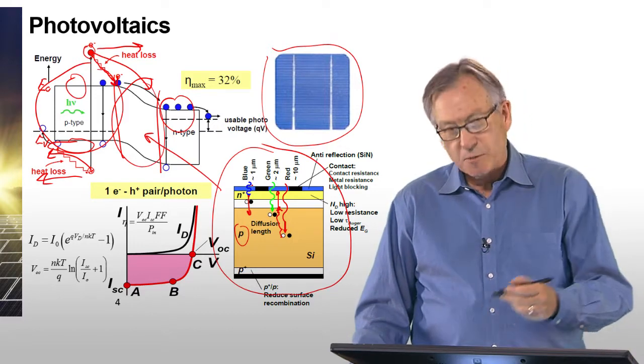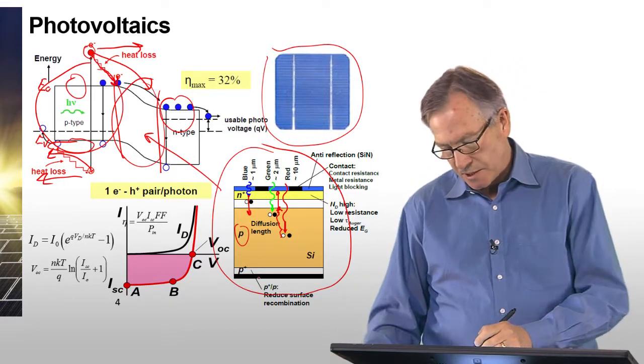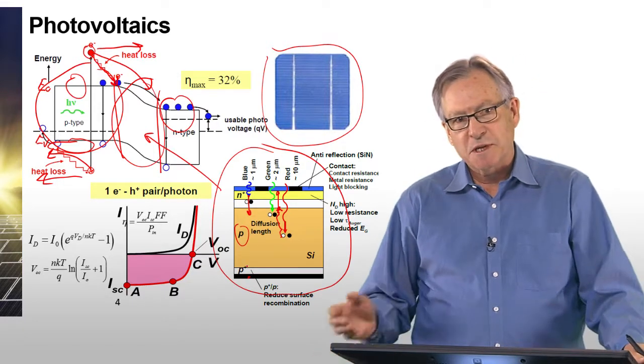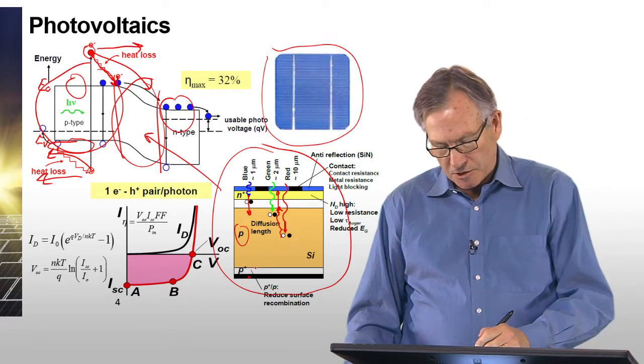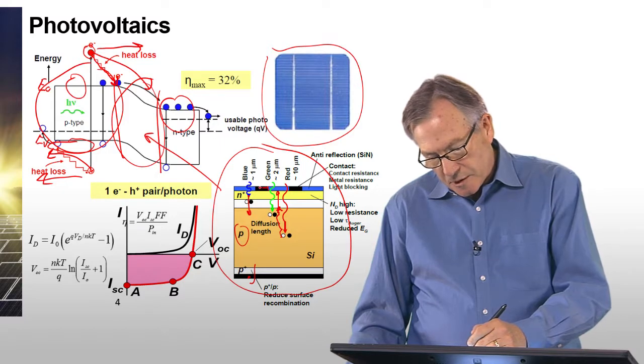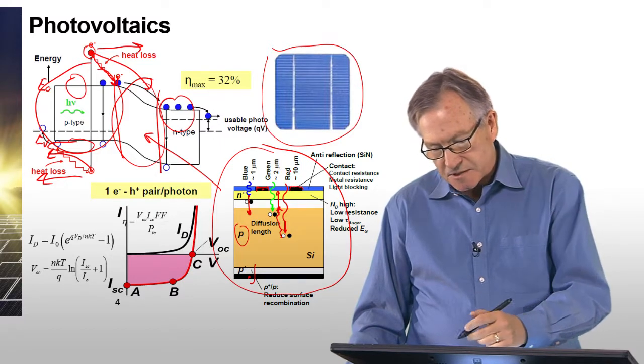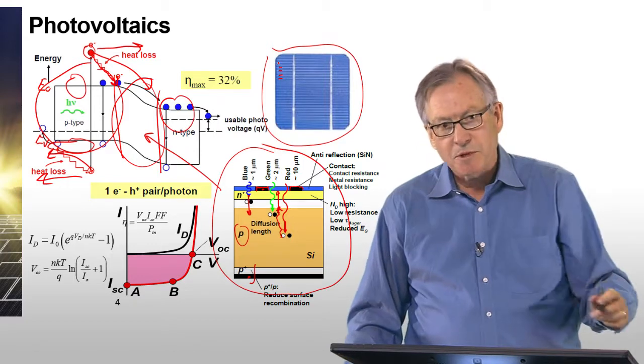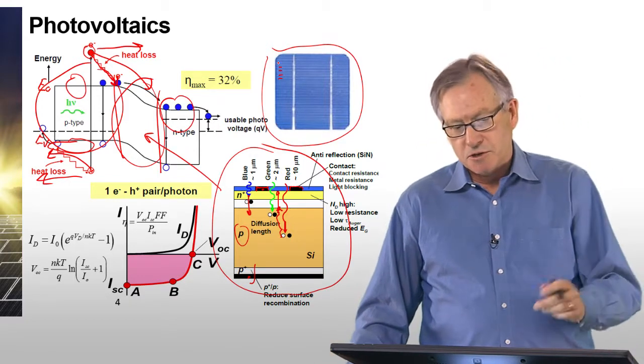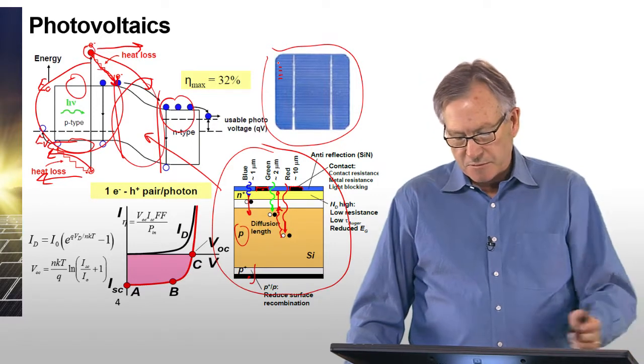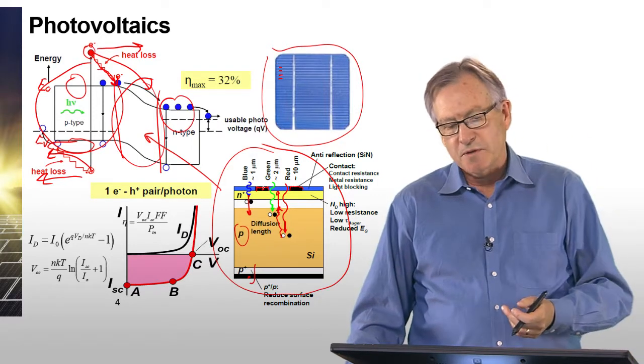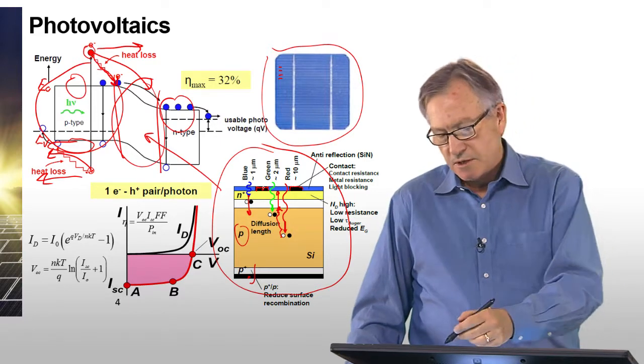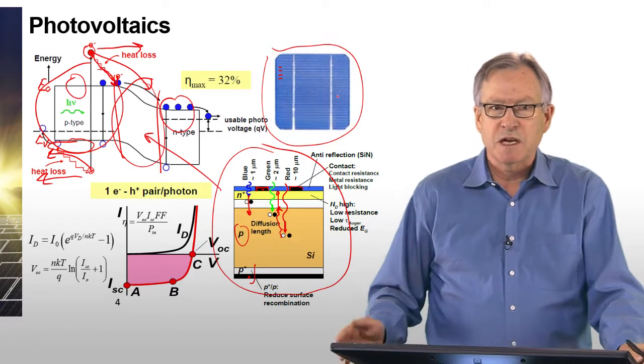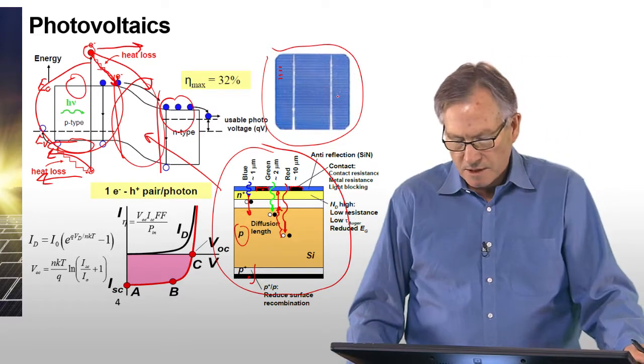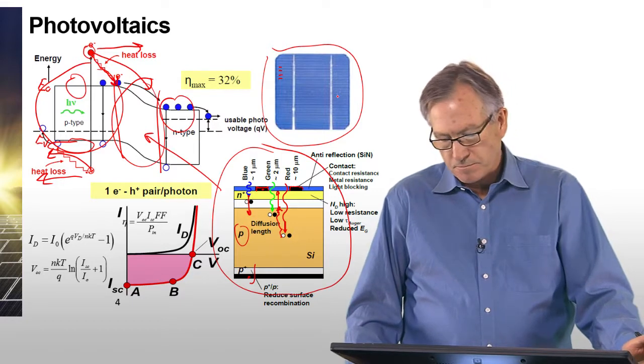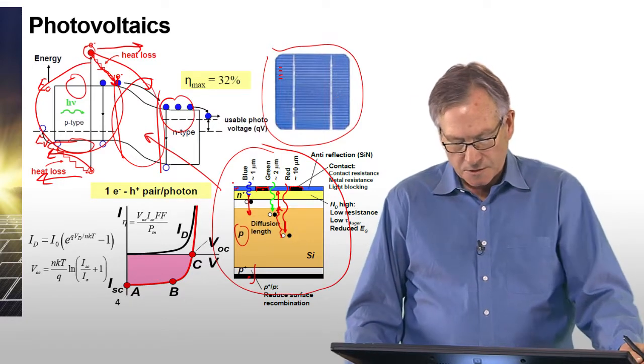And on the top and the bottom, you have to make a contact. You have to get electricity out somehow. So you have what's called an ohmic contact, which makes an ideal contact to the semiconductor and extracts charge out the back. And then you have metal grid lines. These little black areas represent grid lines. They correspond to the same lines that were shown up here. And that's how you extract charge from the surface. This plays a parasitic effect because wherever you have a grid line, it blocks light coming in. So you have to minimize this area of the grid. Typically this grid is designed so that there's less than 5 to 10 percent of shading. Otherwise you lose efficiency of the solar cell. And then the blue just represents the anti-reflection coating.